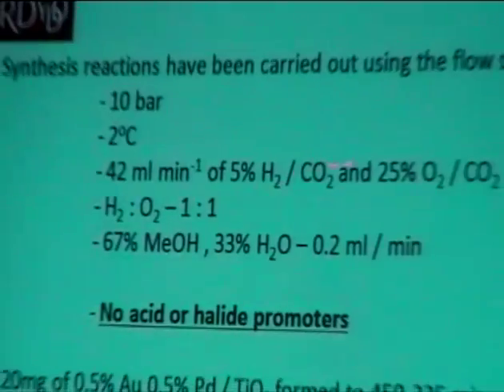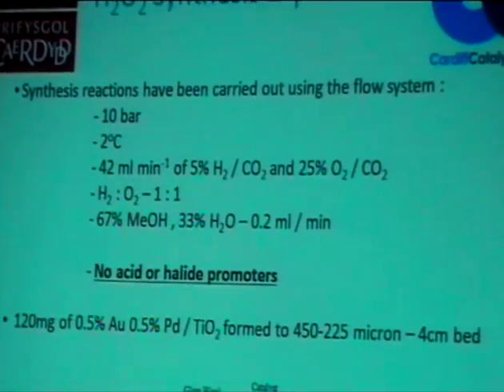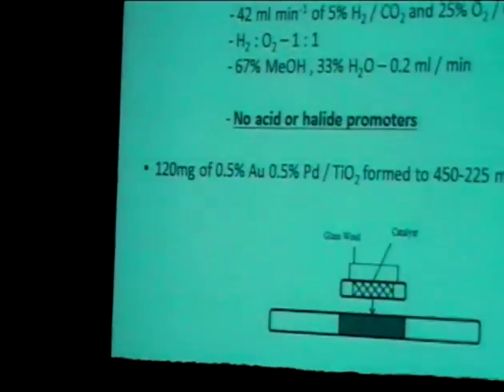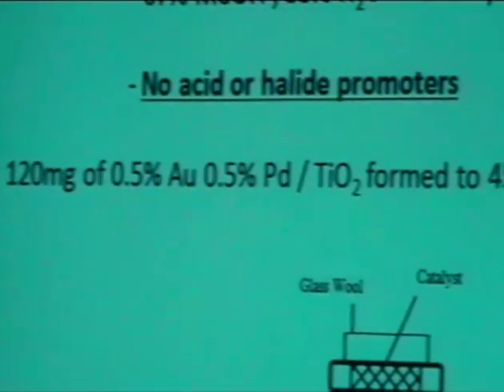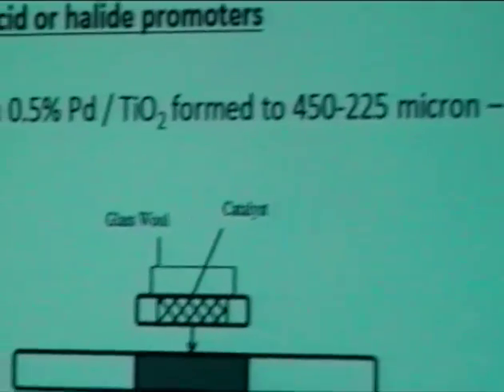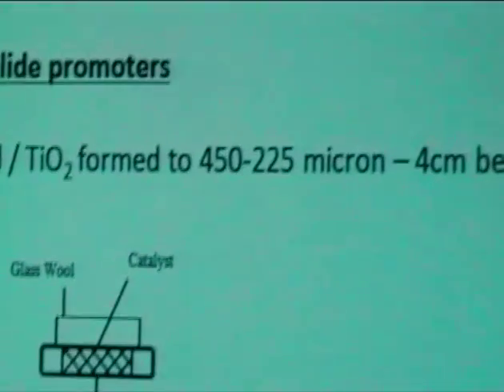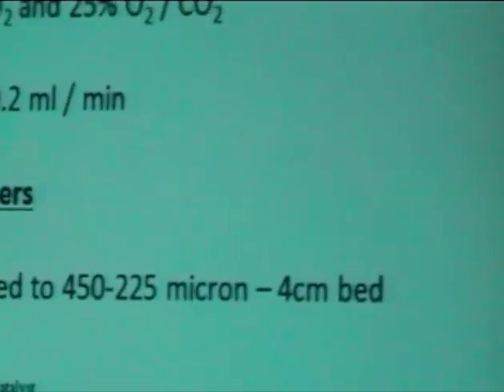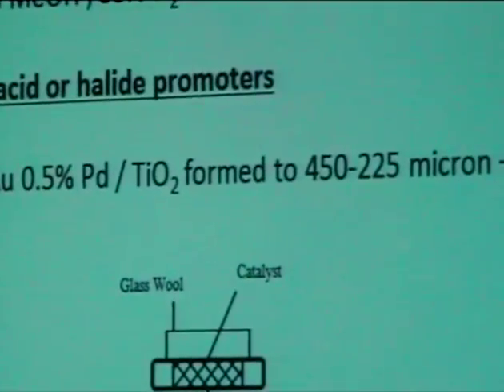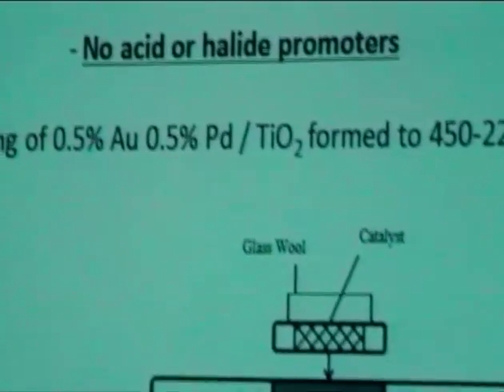So a typical synthesis experiment carried out would be at 10 bar, 2 degrees C. We use the gas flow rate that we determined previously at 42 mL per minute, a stoichiometric hydrogen and oxygen 1:1. Importantly, we're not using any acid or halide promoters, so we do have to consider all the side reactions in this. So I'm just going to flip through some of the reaction conditions that we explored.